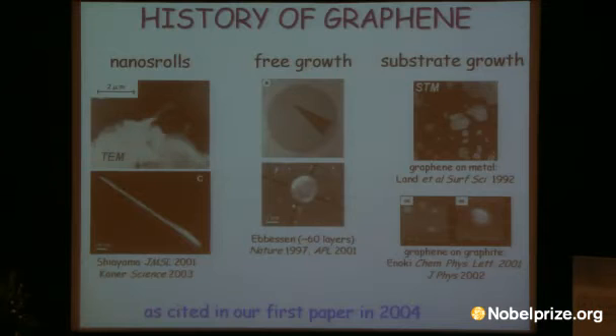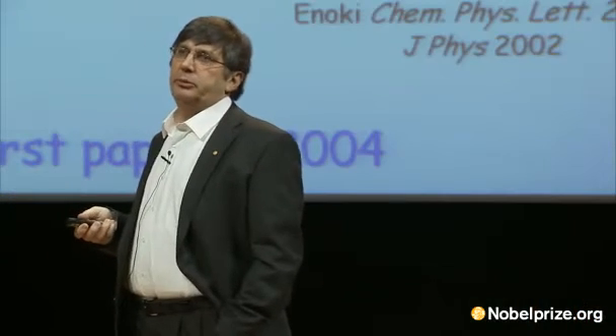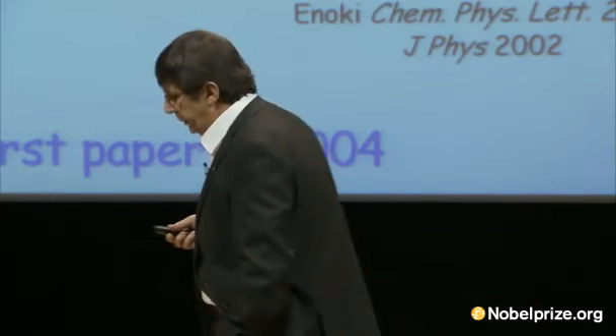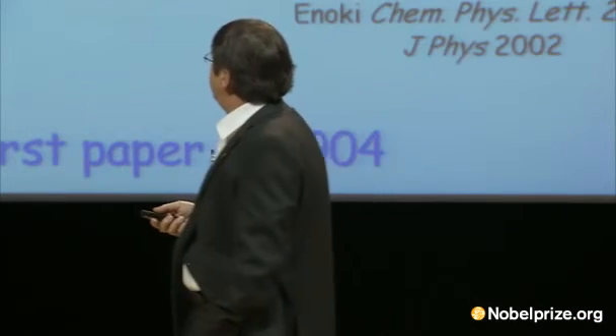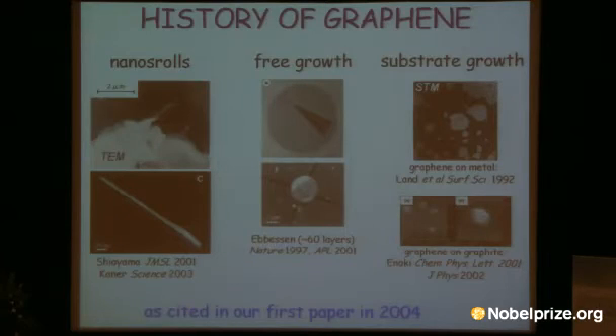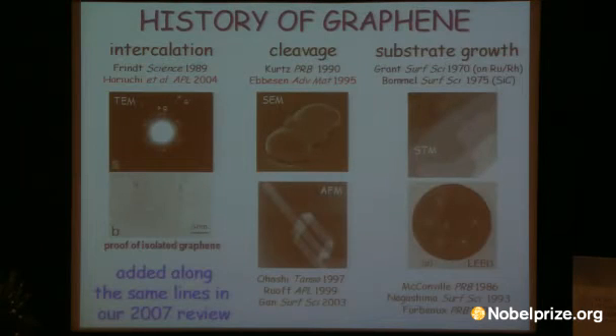I came from a community which never dealt with carbon. It was obviously a different experience for people dealing with graphite and carbon nanotubes. Of course, to publish a paper, you look carefully through the literature. People saw nanoscrolls, and grew reasonably thin graphite films, 60 graphene layers thick. They studied that. People grew graphene on top of metals, on top of graphite, and so on. We added to this literature a little bit later, and I'm pretty well aware of all the history behind it.